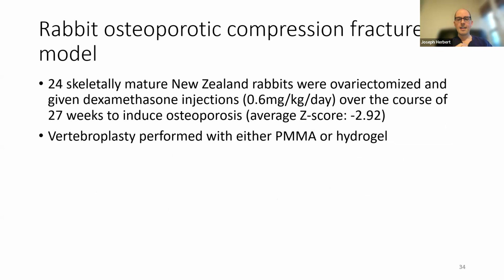So in this particular study that they just presented at NASS a couple months ago, they had 24 skeletally mature New Zealand rabbits. They ovariectomized them and gave them dexamethasone daily over the course of 27 weeks to induce osteoporosis. And they were successful in this. They got an average Z-score of minus 2.92. And then they took these osteoporotic rabbits and did vertebroplasty with either PMMA, which is what is usually used, or the hydrogel.